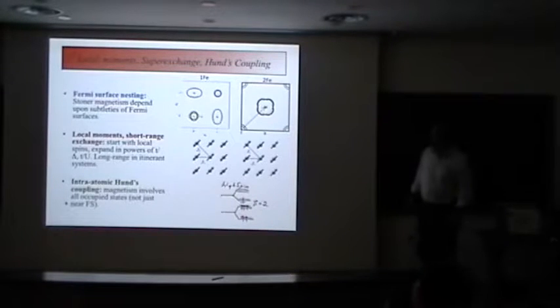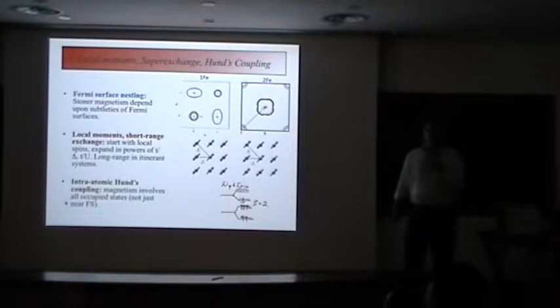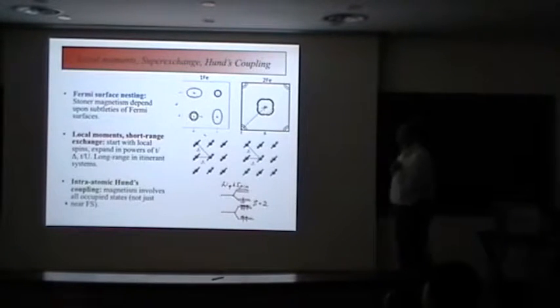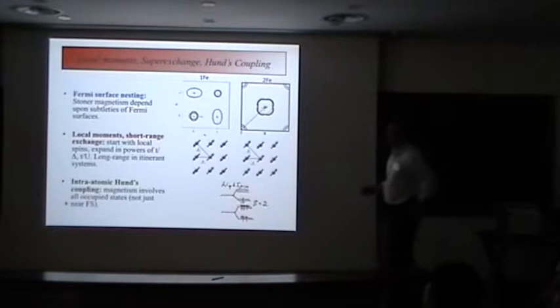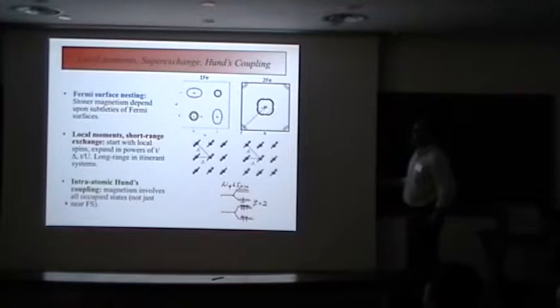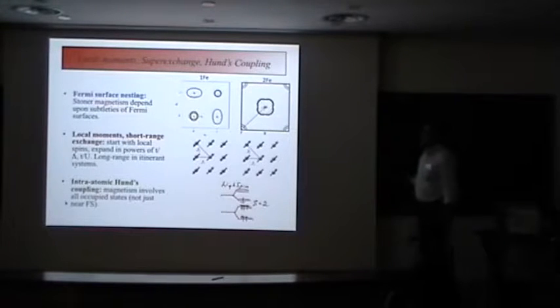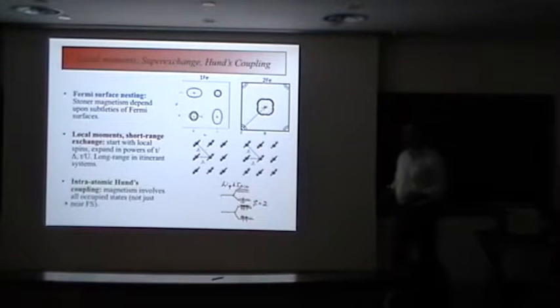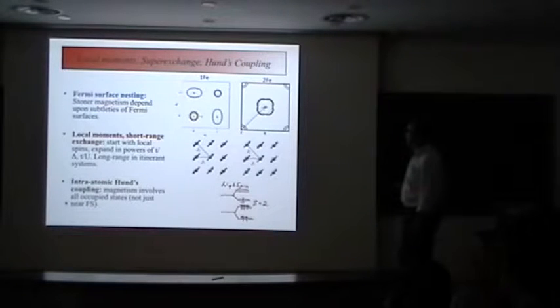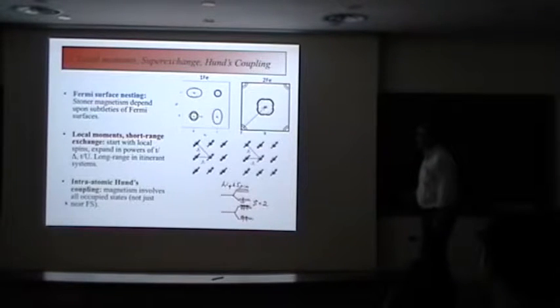So here are three different things to keep in mind when looking at magnetism of these materials. One is that everything is being governed by details of the Fermi surface nesting, how well the hole pocket can be put on top of the electron pocket, and having a nesting condition be satisfied with the pi-zero wave vector that orders them in the one iron unit cell, or the diagonal wave vector in the two iron unit cell.